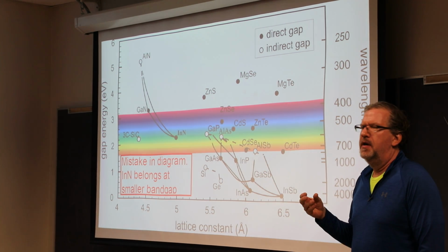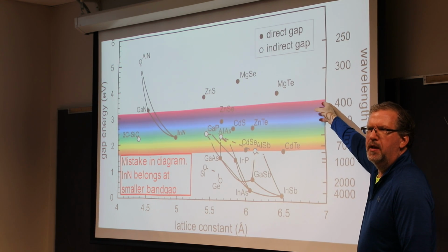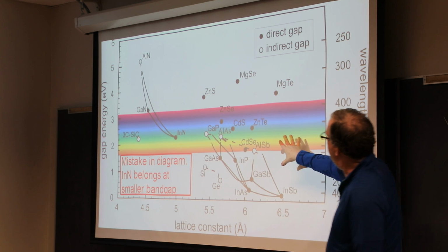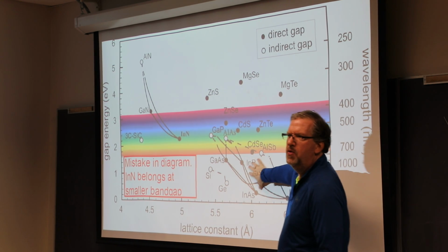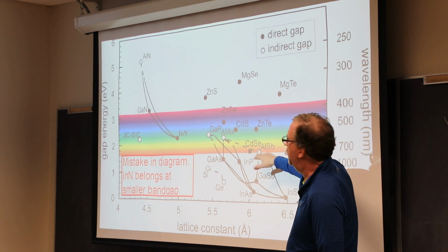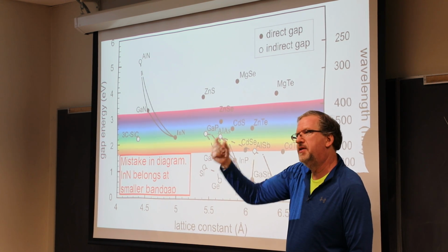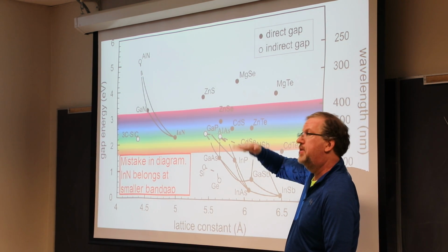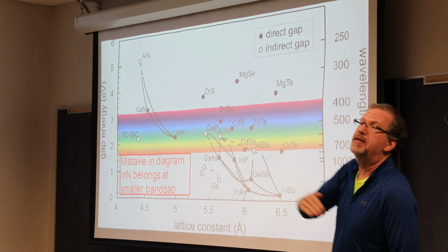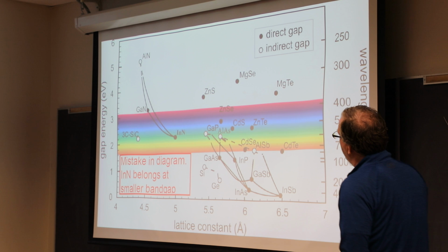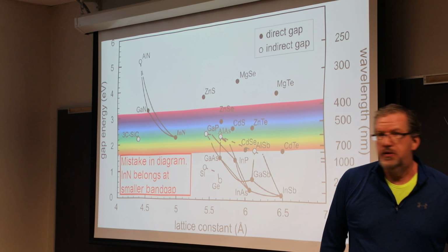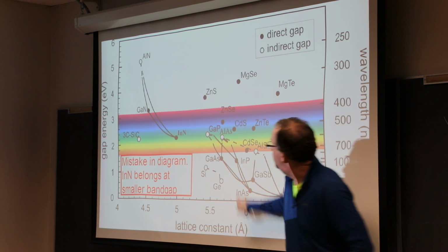there could be where you actually design a laser or an LED for a certain color, and you have to determine the quantum well size. You have to determine what material system you're going to use, and you have to determine what substrate you're going to put that on, and then you have to determine what the thickness of the layers are that are epitaxially grown, and based on the quantum mechanics, the confinement in a finite well, you determine which wavelength that is going to determine. So you could be mixing and matching these different tie lines.